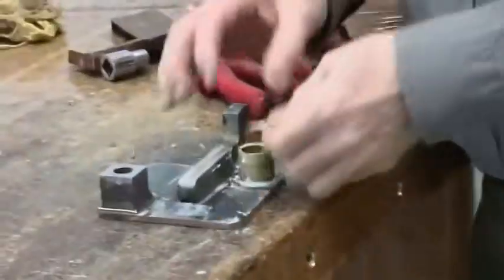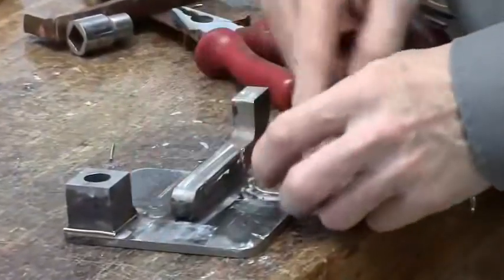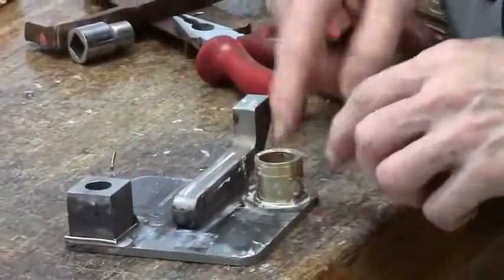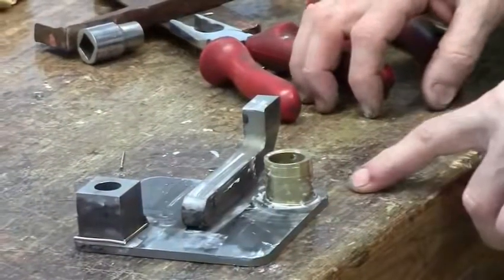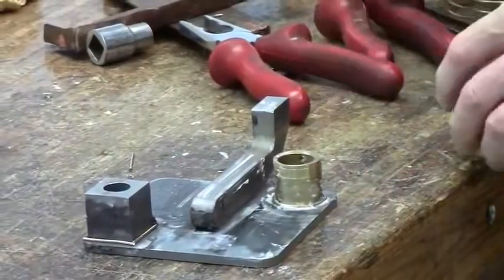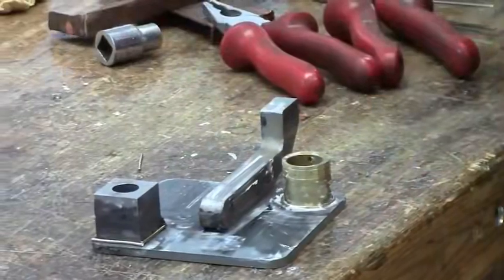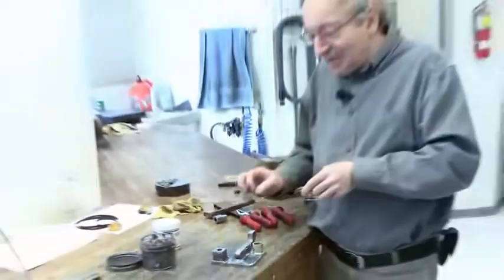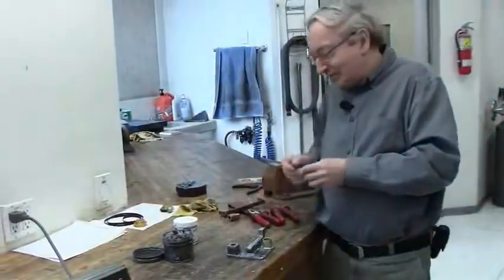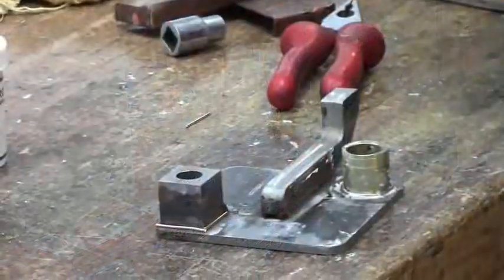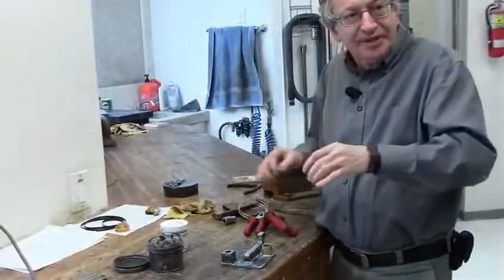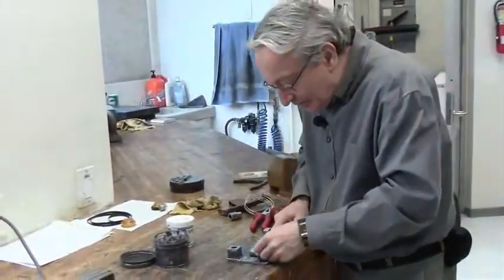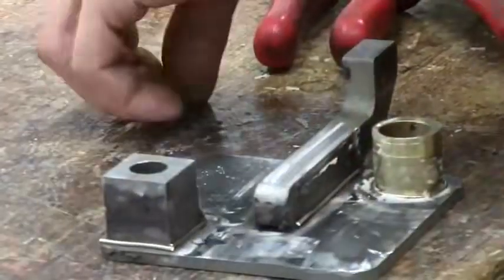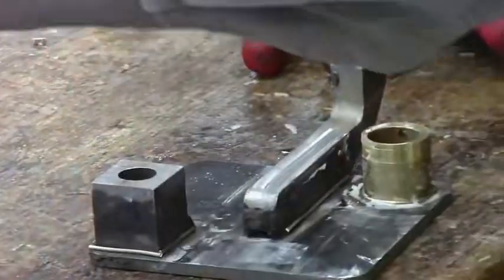Now the gaps can be anywhere from 0 to maybe half a millimeter, because if the gaps are too big, the capillary reaction will be too weak. So you can buy different wires with different abilities to fill gaps, but in general, if the gap is more than half a millimeter, it's not a good idea. It should be machined tighter. You can also get those in foil. So sometimes you have 2 big areas, so you can put a foil underneath covered with flux. Okay? And for good measure, I will just add a bit more flux.